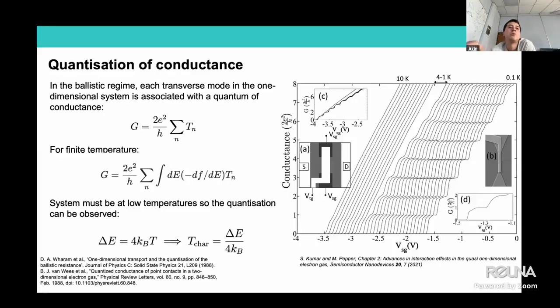The experimental measurements of these systems are done at very low temperatures to see those quantum effects. And you can see that as temperatures increase in this data, this quantization smears out. So the temperatures can vary from tens of millikelvins to up to 4 Kelvin, 3 Kelvin that we would have in the laboratory. So within that range, usually some form of quantization is observed.